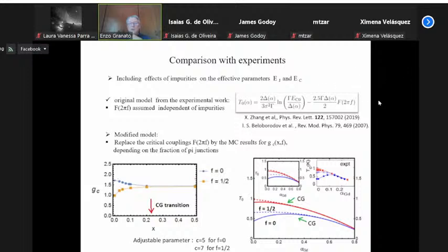So if you take this into account, you replace this function by this behavior here, and you have the results shown in the figure as the main figure here, for two different samples. For zero field, it increases monotonically, and it decreases for f equals one half, with an inversion at a particular point. And this is much closer to the experimental data than the simple model that we described before. So this modeling seems to describe the data with magnetic field, and moreover, it indicates that the point at which the curves merge here is a transition into the chiral glass phase, which is a particularly interesting phase.